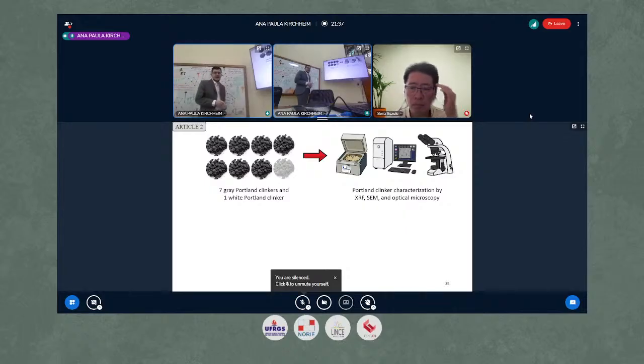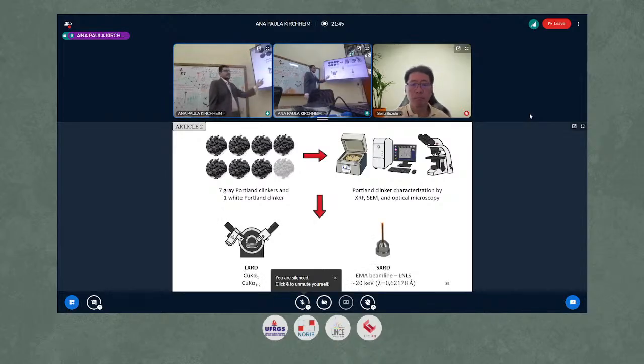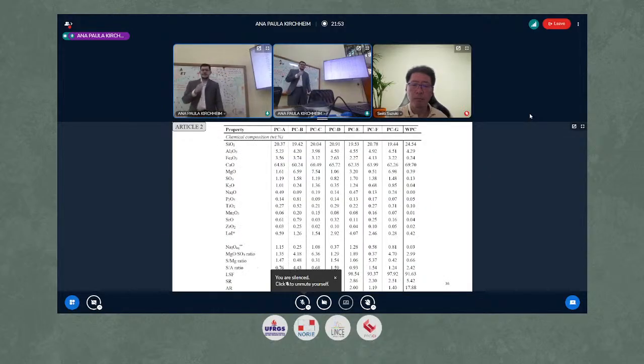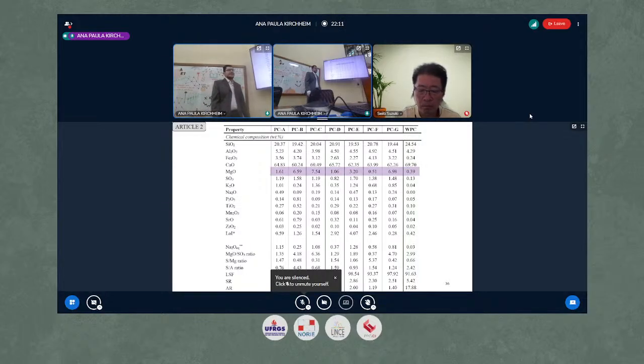We analyzed them by XRF, scanning electron microscopy and optical microscopy, and also by XRD: lab XRD with and without monochromator, and also synchrotron XRD. Here we see the chemical composition of the clinkers. I highlight first that the white Portland clinker has a low amount of impurities, as expected, so a low amount of minor elements. I highlight also the great variation in magnesium, sulfate, and alkali content.